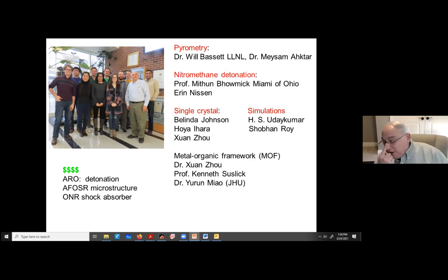Well, you know, you can put thermocouples into the material. They're slow and they perturb. Well, it depends. If your whole career depends on putting thermocouples in there, you're guaranteed to advocate they don't perturb anything, but obviously they do. So I really think optical measurements are the way to go. And the problem here is that when you look in the visible, the stuff has to be pretty hot. And our temperature floor is about 1800 Kelvin if we want to measure the temperature in 1 nanosecond.